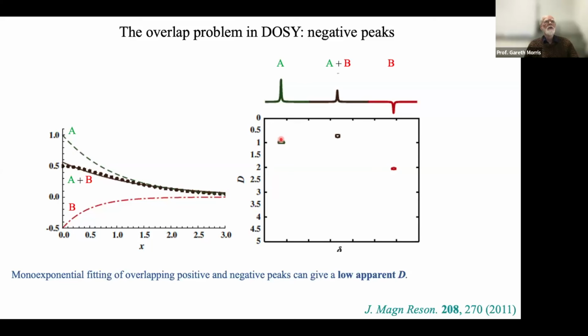And now things are even worse. Here are A and B. Now we have A is slow and B is fast. Goodness knows why that was. But still, when we have one of them negative and one of them positive, when we add them up, they're a bit less like an exponential now, but they still can decay away. And sure enough, we actually see, instead of a diffusion coefficient that's intermediate, we see that it's actually below the lower diffusion coefficient.